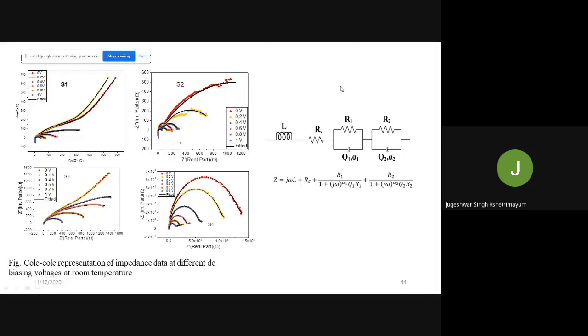Because if I have a polymer, when I dope the polymer, the polymer is just a chain. In the chain, I put in some ions. Because of the ion environment, it affects the surroundings. When you apply the electric field, one island of charge is there. When another charge comes here, some repulsive or attractive interaction must happen inside the polymer. Because of this, a capacitor effect may be formed. That capacitor is not exactly a capacitor, but it behaves like one. That's why we call this Q a constant phase element.